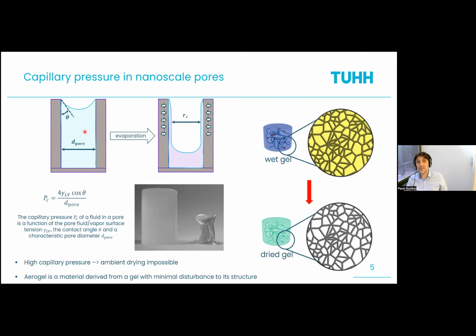And this basically means that you have a difference in pressure between the gaseous phase and the liquid phase. And as soon as you have a difference in pressure anywhere, then this pressure is going to do something to your structure. And this capillary pressure is exactly the same thing. It's going to collapse your structure. If you try to dry any gel, or an apple or, for example, a grape, in an oven, you see how quickly the structure collapses. This is also applicable to chemical gels. This is a nice example of silica gel, a hydrogel, which is being dried and then loses all these nice properties.